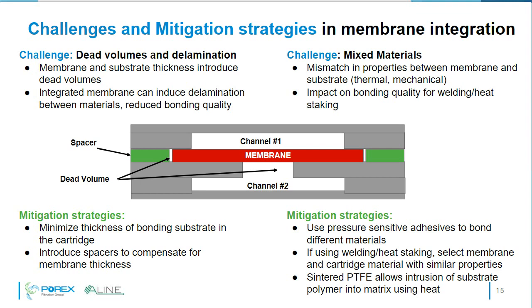In order to mitigate this challenge, we typically try to minimize the thickness of the bonding substrate in the cartridge to reduce that volume below the membrane, and introduce spacers, shown in green in the schematics here, that can help compensate for the membrane thickness and avoid that type of delamination. Another challenge that typically comes up as part of this integration is the use of mixed materials. That can induce mismatching properties between the membrane and the substrate that can impact the bonding quality for welding, heat staking, or interfacing between the different materials. To mitigate that, one option is to use pressure-sensitive adhesive to create a bridge between different materials and bond them successfully. If using welding or heat staking, it's typically good to select a membrane and a cartridge material with similar properties.